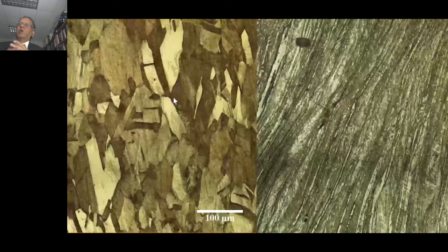So what more can we diagnose? How much more can we extract from the experiment? These are images of the copper grains prior to the loading, and on the right-hand side, after the loading, when the specimen has failed. And you can see grains that were about 20 or so microns in width have now gone to something that are about 2 to 4 microns in width. They've elongated significantly, roughly 10 times their initial length.